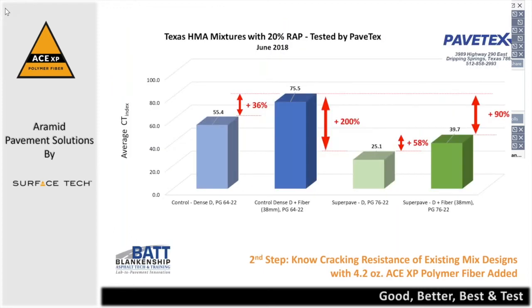So I'm going to walk through some of these ideal CT tests that we've done, three or four of them from around the country. One of them starts from Texas, and we had PaveTex run this for us. This was actually a Tex-DOT mix, a dense grade, as they call it down there, with a 64-22, 20% wrap. As you can see on the left, in the blue numbers, we have an ideal CT of about 55.4. And when we added one dose of the aramid fiber, we went up to 75.5, or about a 36% improvement. Now, think about this for a minute. Their Superpave mix in Texas is actually a 76-22 binder. We don't always associate a 76-22 binder with good crack performance.